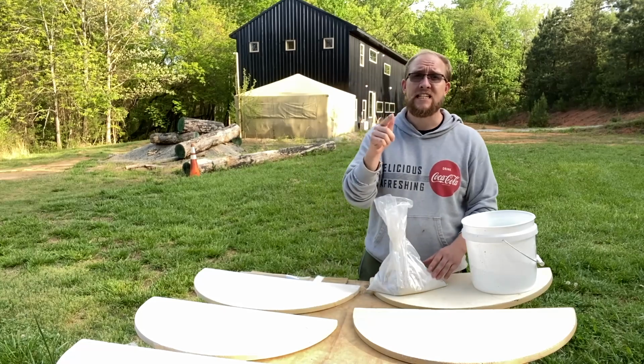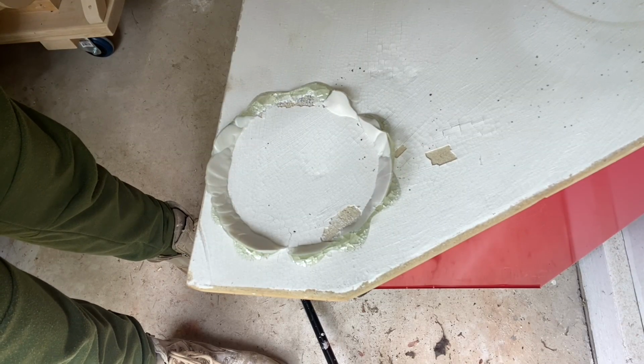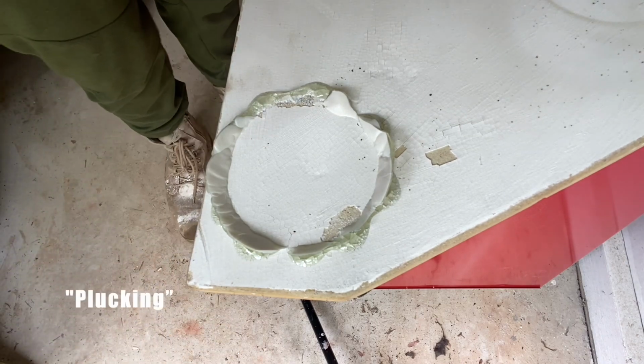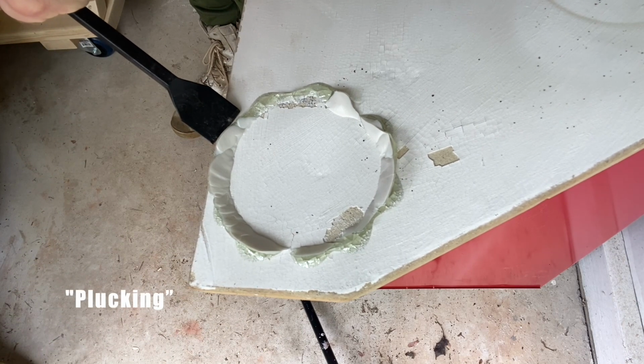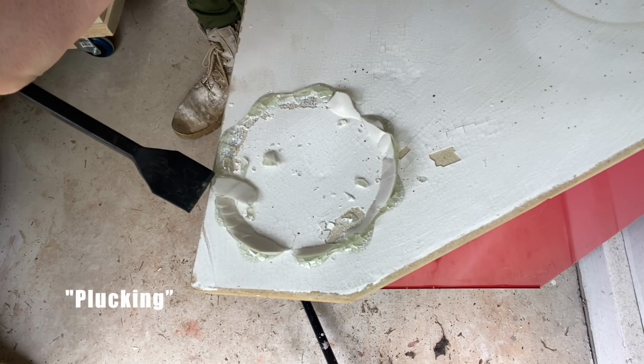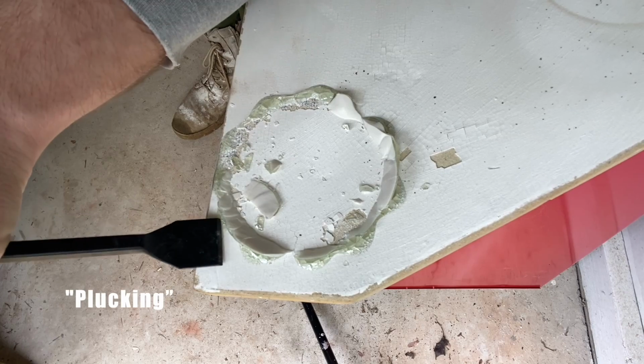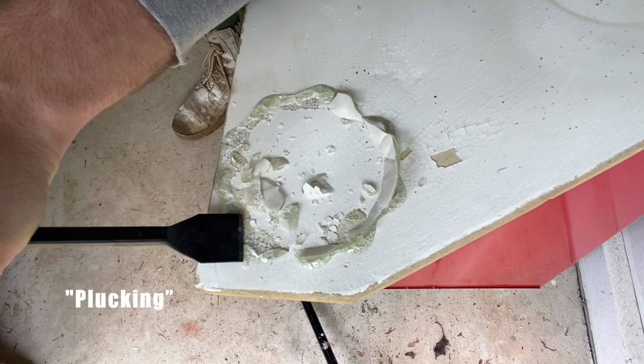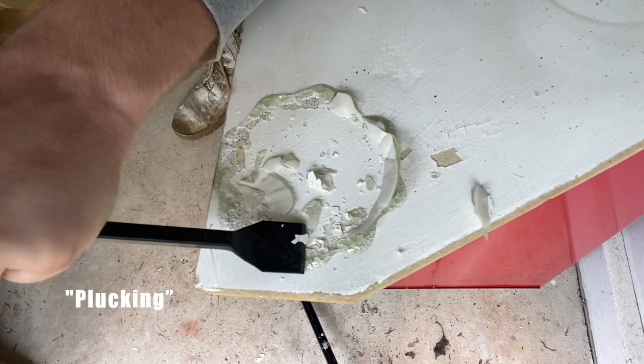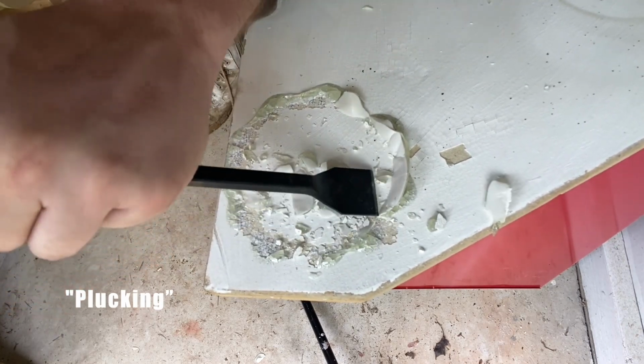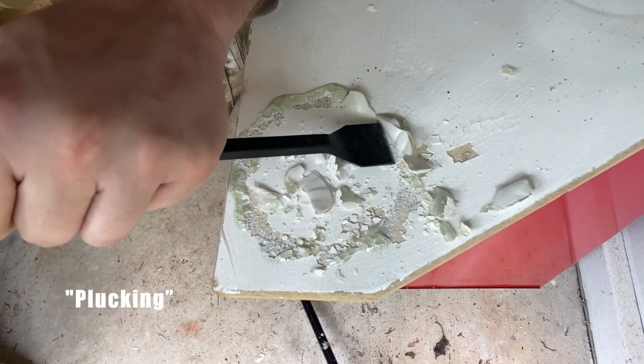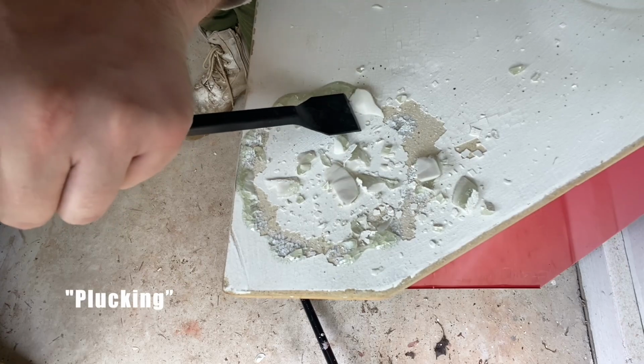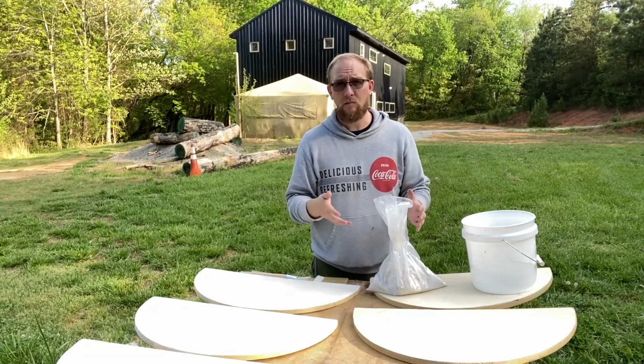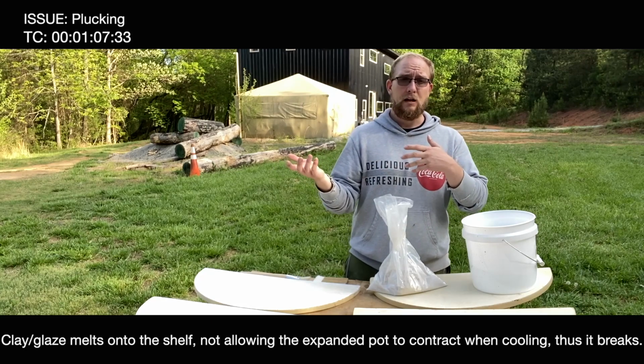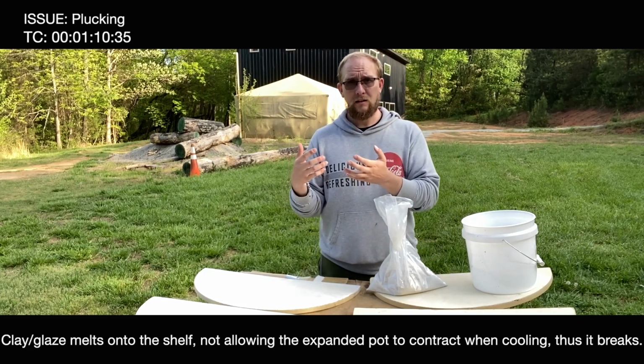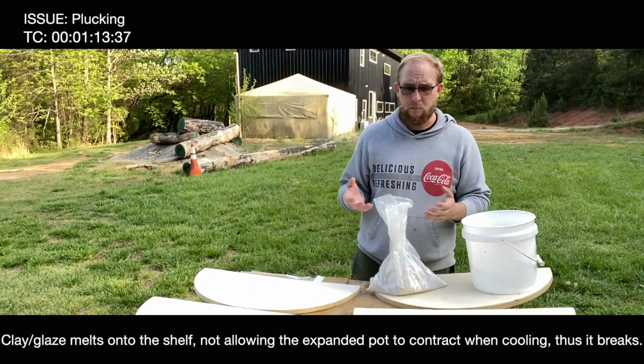Also, you want to make sure that you can save your pots. When clay and glaze get stuck, a lot of times what happens is what we call plucking. Plucking happens more often with porcelain that becomes glass-like, but also stonewares and earthenwares, where you have clay bodies melting, or you have glazes melting and attaching itself onto the shelf. And when you go up and pick, it more or less takes the bottom out. You have shards that stick. So the bottom of your pot is completely gone, okay? So that's what plucking is. This is very common with glazes and porcelain. If the glaze gets stuck, and then the porcelain will also be stuck, and you won't have a bottom.